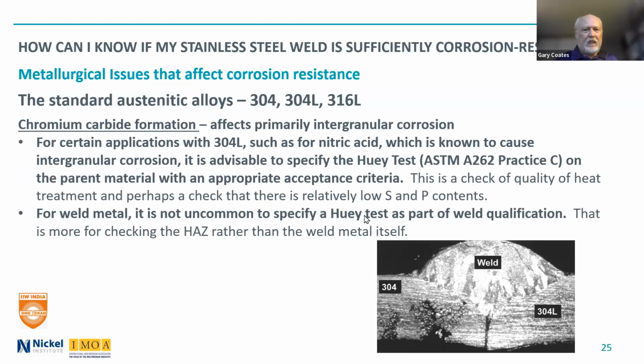And I think even in Europe, they want it done, but it really doesn't tell you a lot. But certain applications, and I take the example which is the most common one that I run across regularly, is nitric acid service. When you're using 304L in nitric acid service, especially at the higher concentrations, like 65% and close to the boiling point, you can get it even in the L grade. And so they will specify the Huey test, ASTM A262 Practice C, on the parent material, because they want to ensure that the parent material is fine. And if it can't pass that, there's no hope of doing a good weld on it. So this is really a check of the quality of the heat treatment of the material, and perhaps a check that there are relatively low sulfur and phosphorus contents.